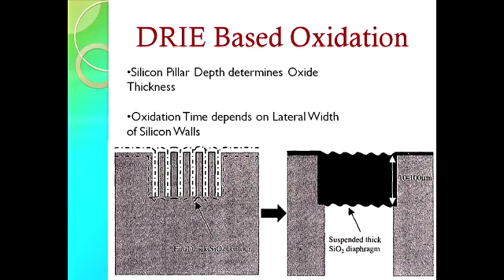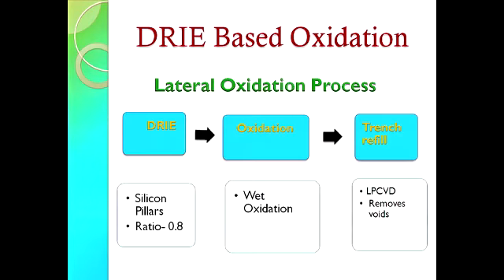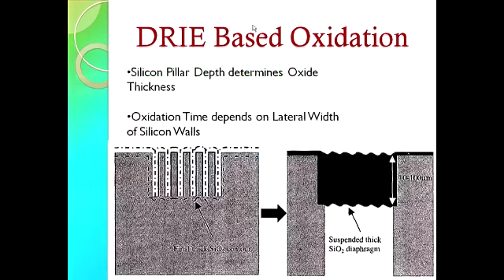You said something of aspect ratio 0.8, right? Yeah. This specifically has to be 0.8? We're talking about the aspect ratio. Approximately 0.8, so that we get a completely oxidized layer. Why does it have to be just 0.8? Why can't we make the pillars thicker? Yeah, we can have like 1.5, around 0.8 we can have, but I don't know why they've chosen 0.8, but it was stated that 0.8 is a perfect ratio for having a good oxidized layer. So for example, here the pillar thickness was 2 micrometers and trench thickness was 1.5 micrometers.